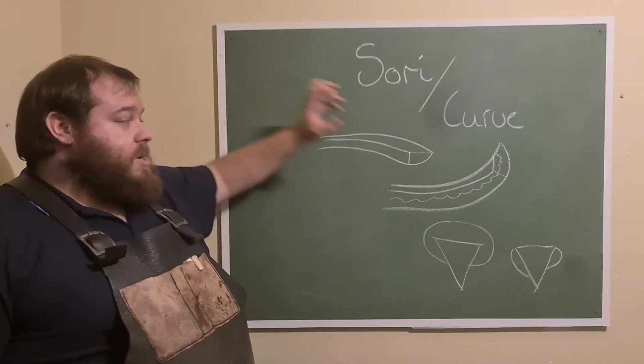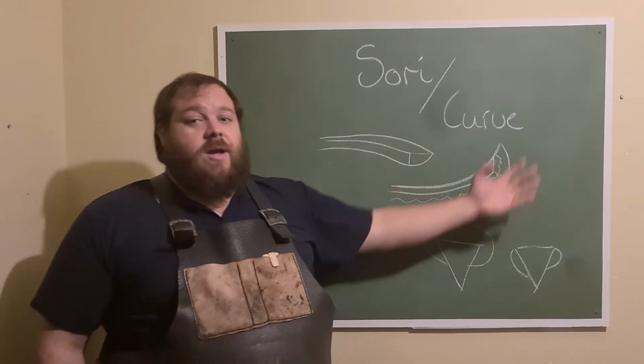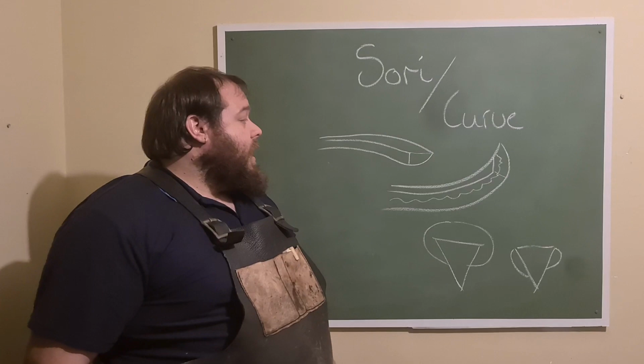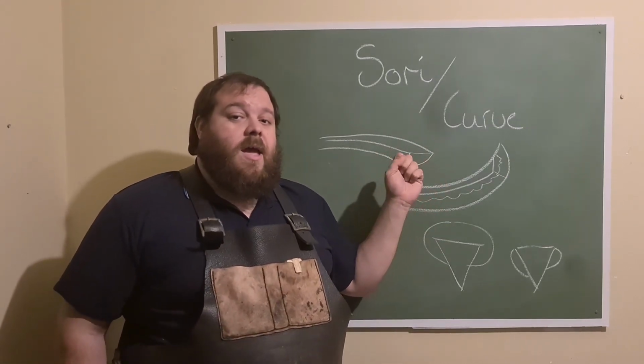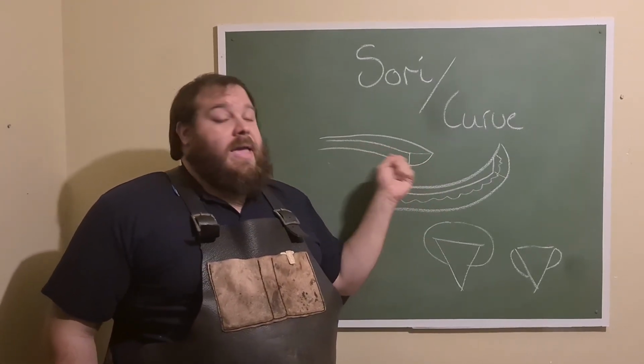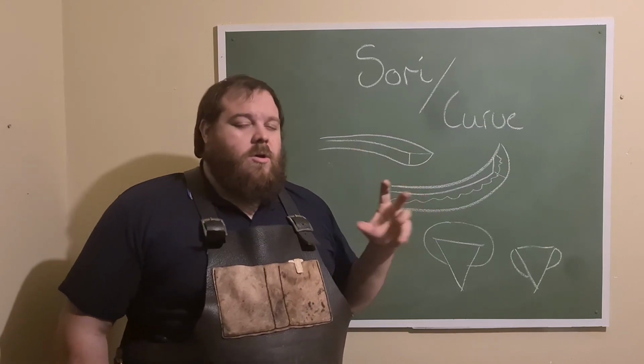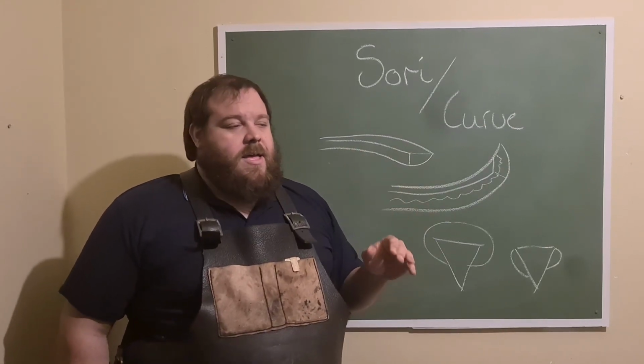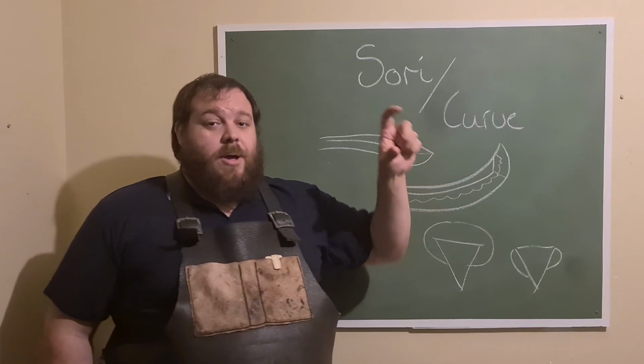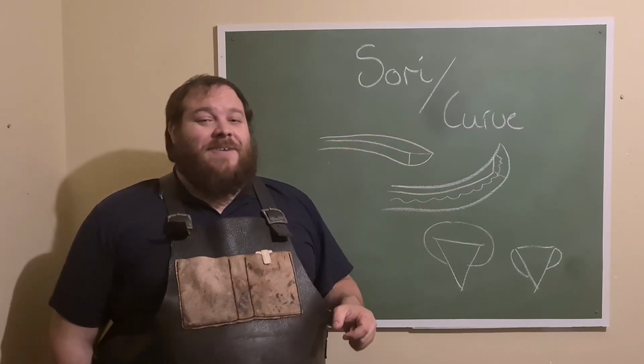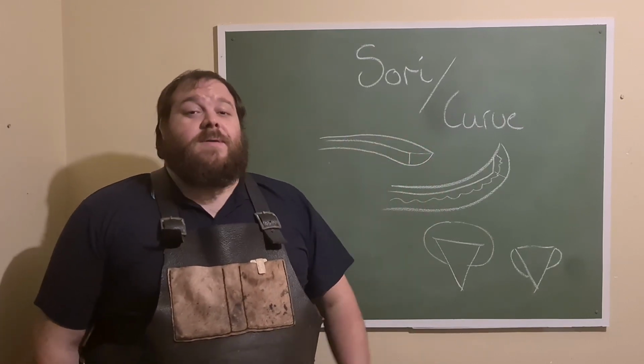This is why the Japanese tend to use water, is because they're trying to create that curvature. So just be aware of that if you are going to use a high-speed oil, that you may get counter curvature, which is not always a serious amount, but I have seen some blades look like Persian fighters by the end of their quench. So just be aware that that's a possibility.